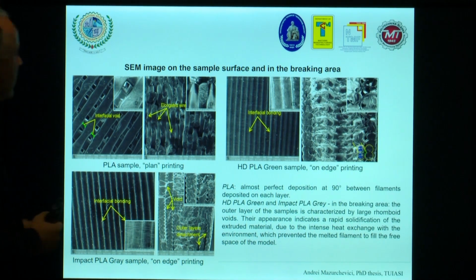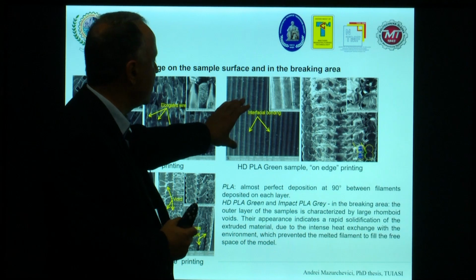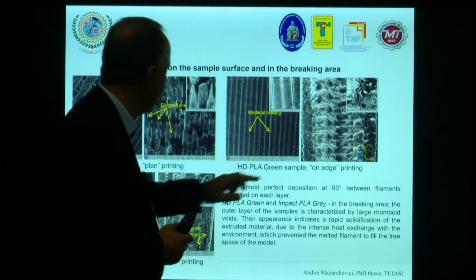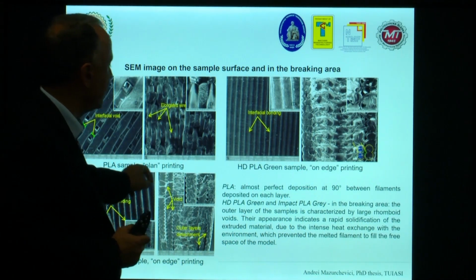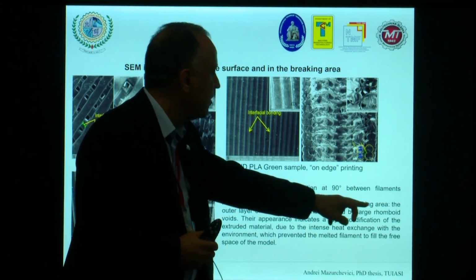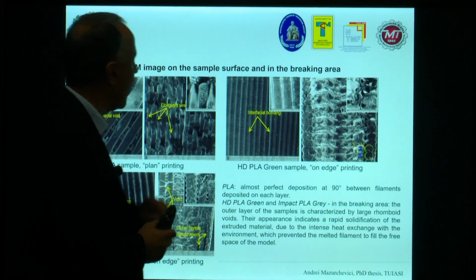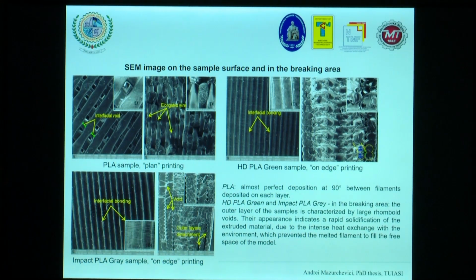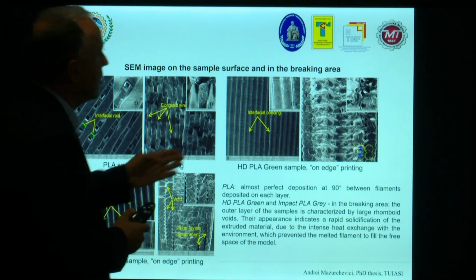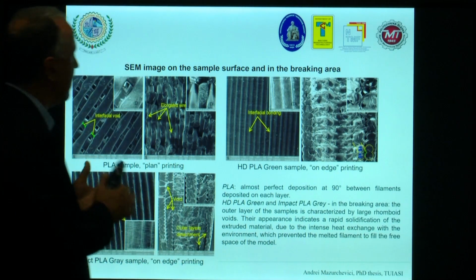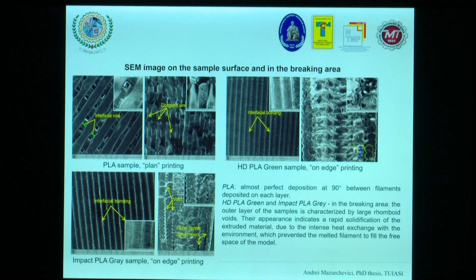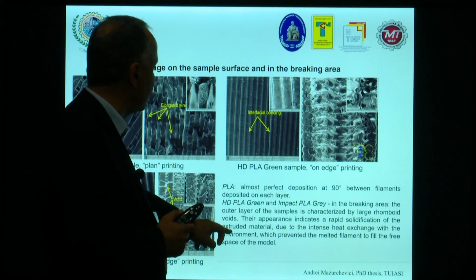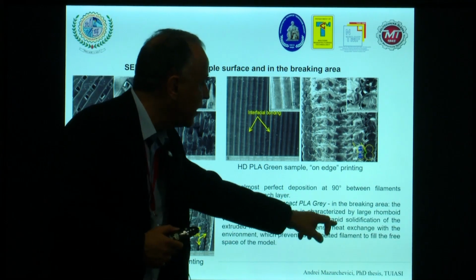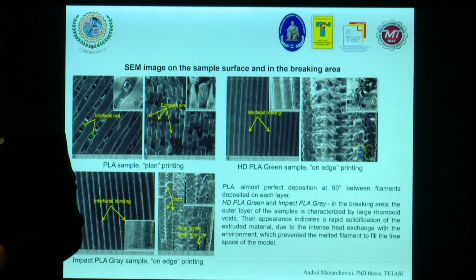In case of high density PLA green sample on edge printing, here was on plan printing, you can see on the breaking area the outer layer of the sample is characterized by large rhomboid voids from this point of view. Their appearance indicates a rapid solidification of the extruded material due to the intense heat exchange between